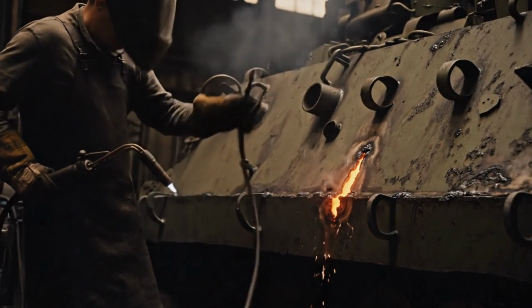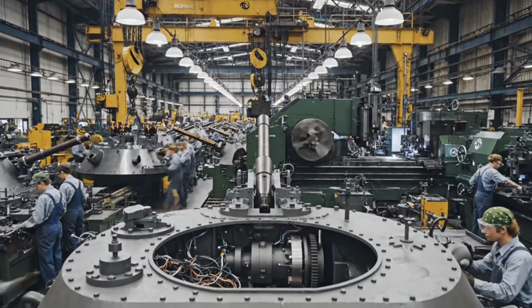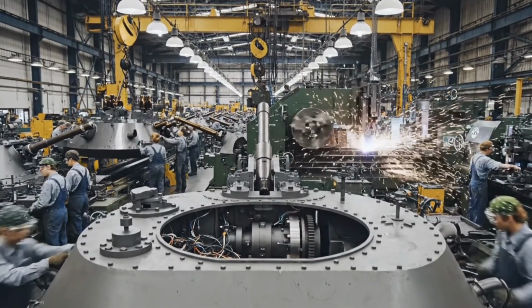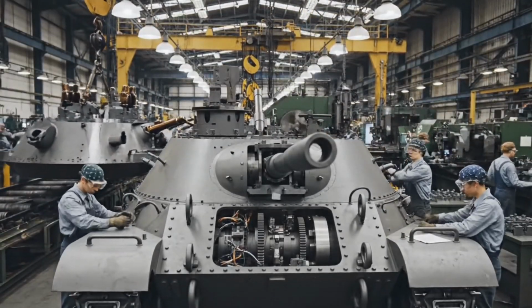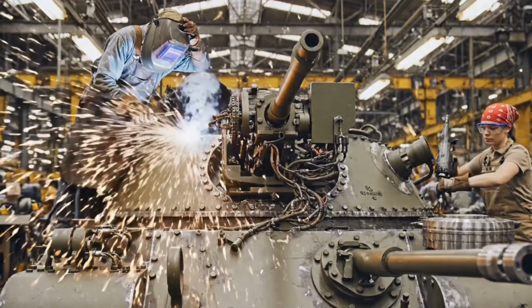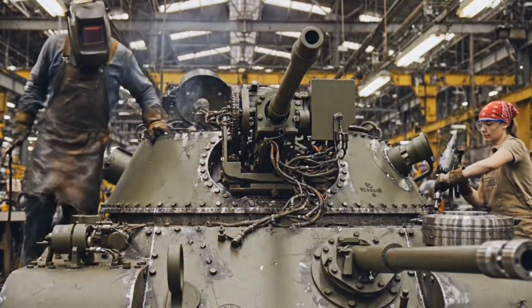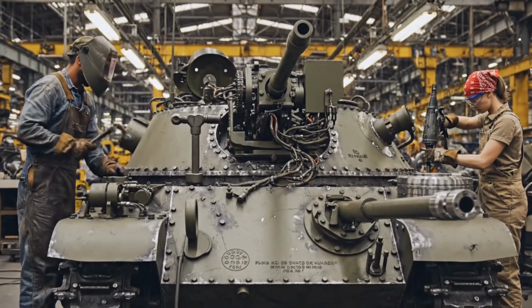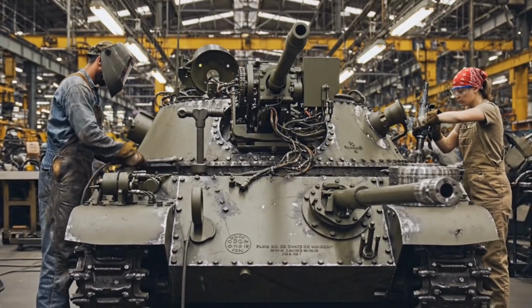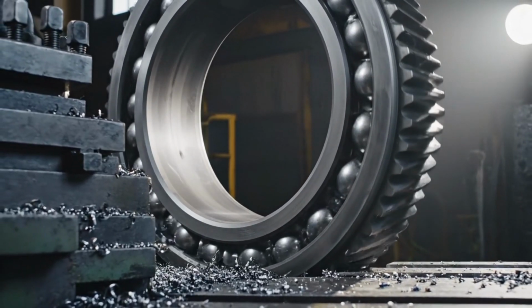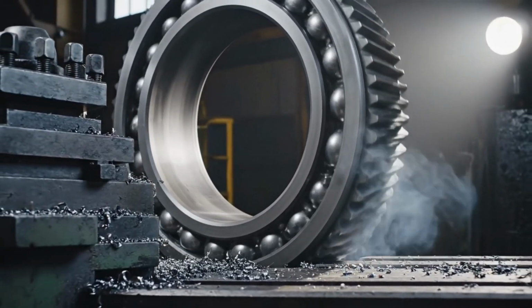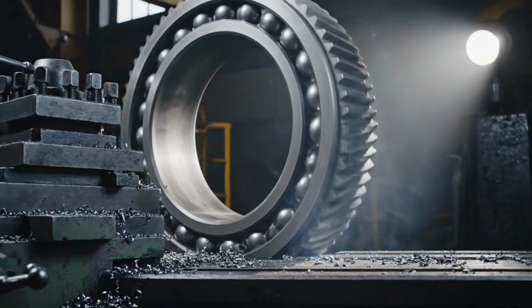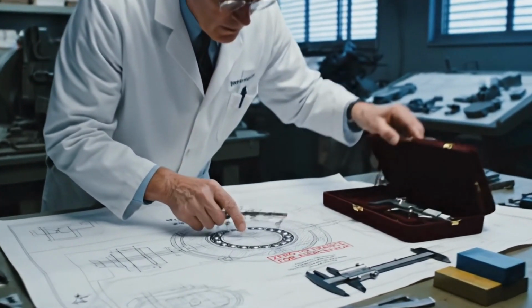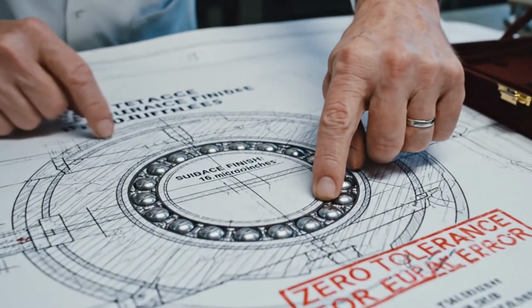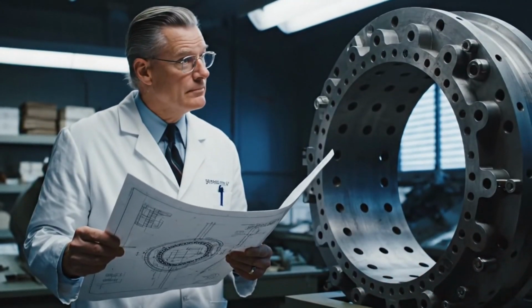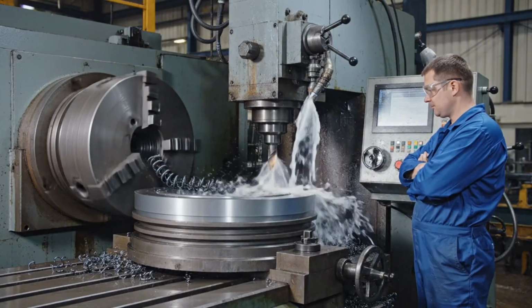The turret was manufactured in a separate facility within the same plant. It was a more complex piece than the hull, with a rotating mount for the 37mm M6 gun and a coaxial 30 caliber M1919 machine gun. The turret ring, the circular bearing assembly that allowed the turret to traverse, was precision machined from a single forging of high-strength steel. This component had to be manufactured to tolerances of just a few thousandths of an inch, because any wobble or binding would make it impossible for the gunner to track targets smoothly.